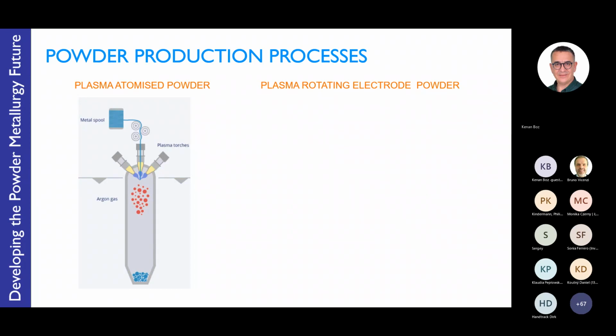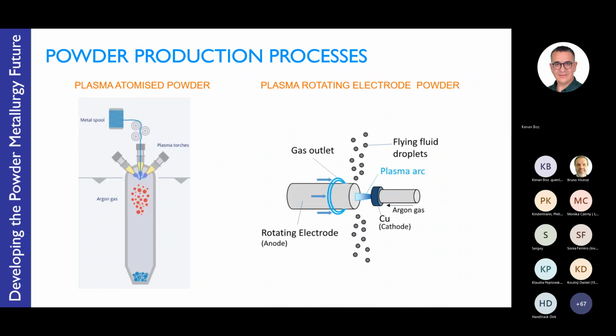And here you can see an arrangement of plasma torches, which provide both the heat to melt the feedstock and the gas supply to atomize the powder. And plasma, at the end of the day, is basically very hot gas. And a very well-established process for additive manufacturing as well, providing a range of different sizes, typically a coarser to mid-size fractions. Then we have a very well-known process called the plasma rotating electrode production process.